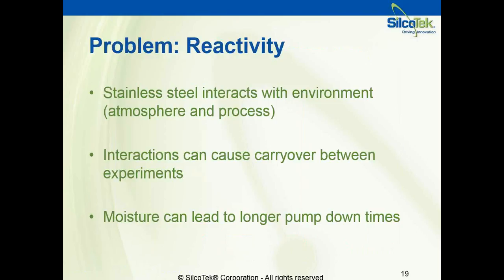Another problem that's very common and one that we're very familiar with solving is reactivity within the chamber. So a stainless steel surface alone can be a catalyst for various interactions which will cause absorption within the parts. So these interactions cause carryover between experiments, between different maintenance cycles, between different processes, and this will change the expected outcomes. It will impact your yields. And from a vacuum standpoint, moisture and reactivity can lead to pump down times that are extremely long.